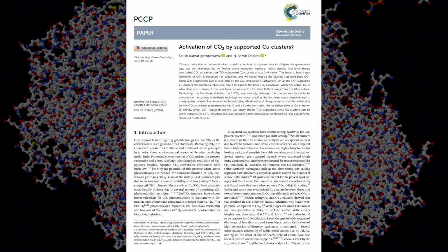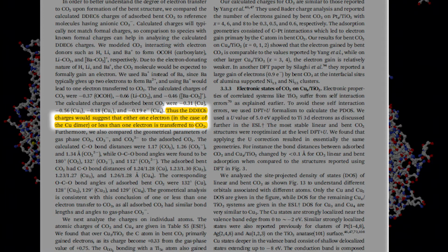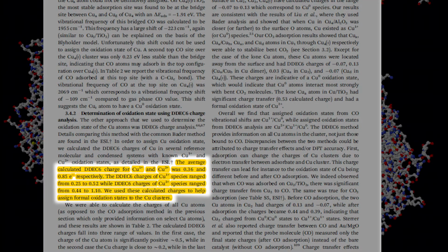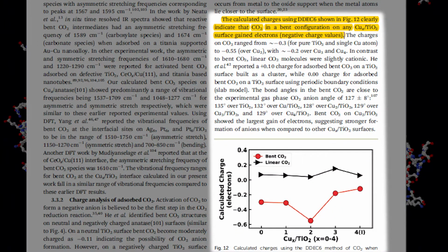In another study, CO2 was activated via catalytic reduction with titanium dioxide supported copper clusters. DDEC6 was used to inspect the charge transfer from copper atoms to a titanium dioxide surface. It helped conclude that one electron or less was transferred to CO2, as well as the oxidation state of copper and the conformation of CO2.